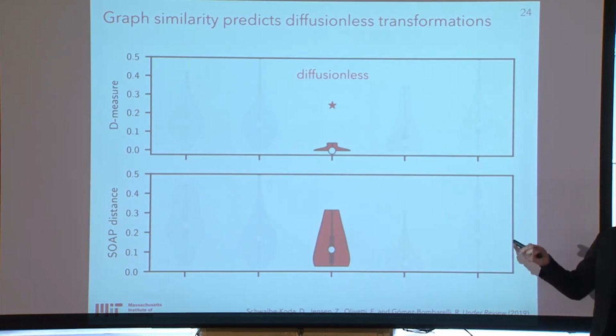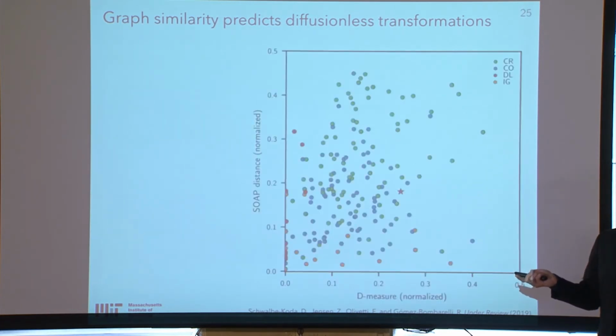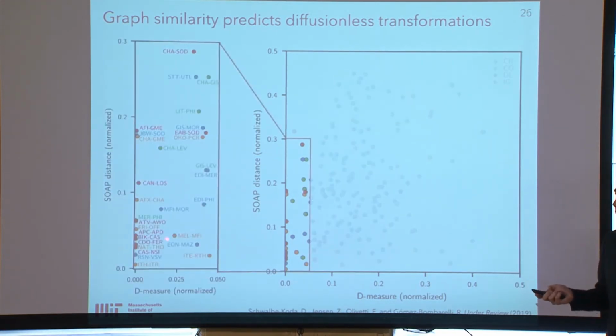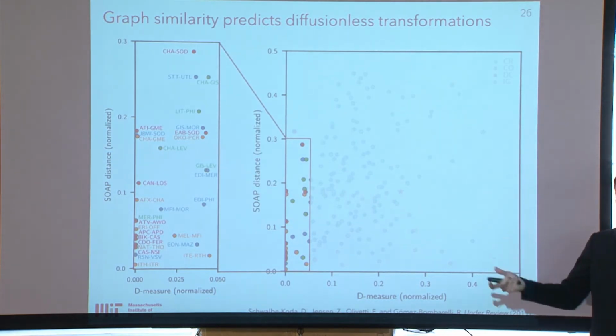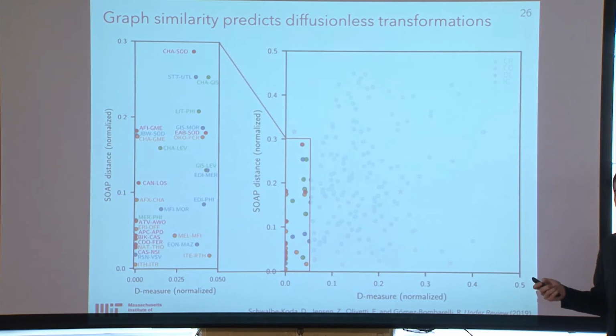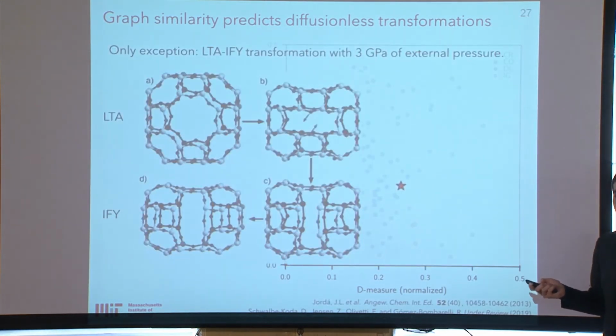But most interestingly is when we plot these two pieces of information in the same XY plot. Here in the x-axis, you have the graph distance between 2 zeolites, and in the y-axis, you have the structural distance between these 2 zeolites. And each one of these points is an experimental observation of a zeolite interconversion. We see, as I mentioned before, that all diffusionless transformations, represented by these red dots here, fall on the low graph distance part of the plot. All but one, and there's one single exception, which is the LTA-IFY transformation. It requires an external stress of 3 gigapascals, however, to make this transformation work.